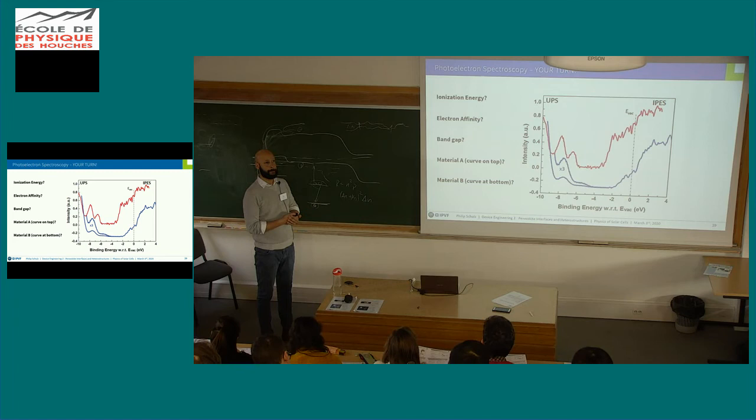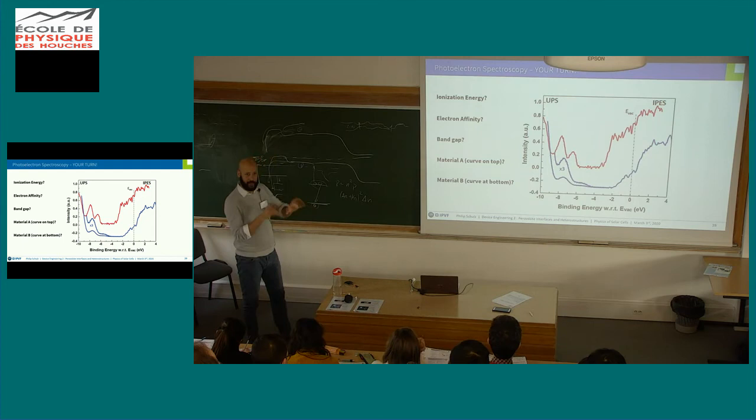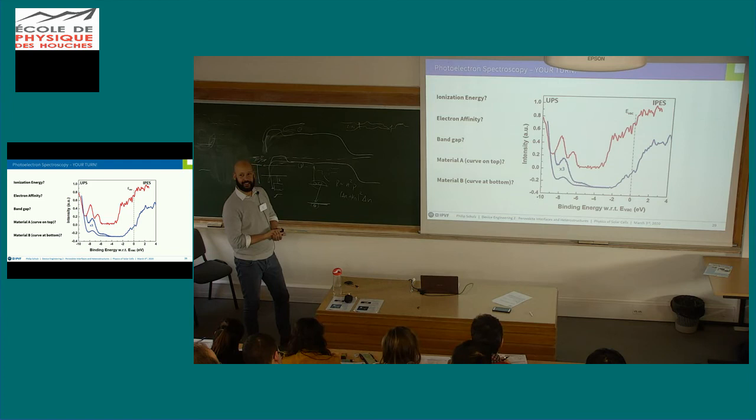Okay, so that's also good, because if you compare those two and you align them to a common Fermi level, you would see that here the conduction band is closer to the Fermi level, which makes it an n-type semiconductor. It's actually an organic molecule, a fullerene, C60 type molecule, ICBA. And the blue curve, what is that? It's also an organic molecule. Here it's a rather p-type donor polymer, P3HT.